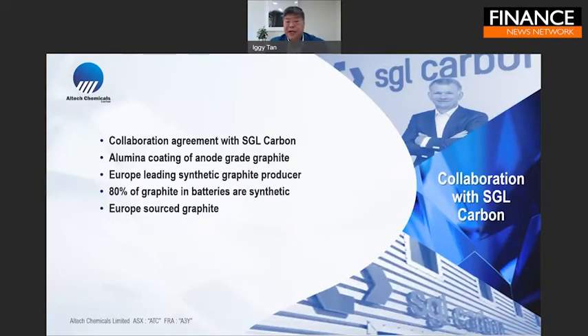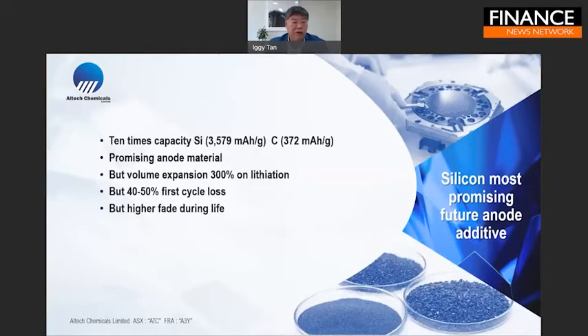We have recently signed up an MOU with SGL Carbon, one of the largest European graphite producers today, and they're very interested in us coating their graphite with the alumina coating. So we are partnering them as we go through. As I mentioned before about Tesla and the increased use of silicon in the anodes, now silicon is a very promising anode material. The reason is it's got 10 times the capacity compared to graphite. So there are 10 times more active sites that the lithium can sit in. And so it's actually a very promising material.